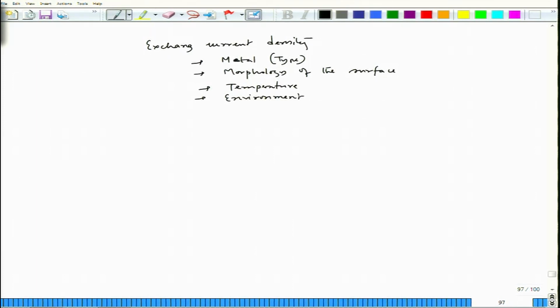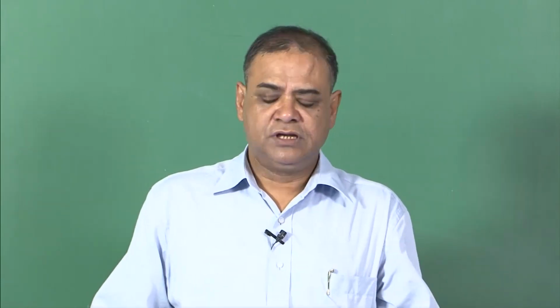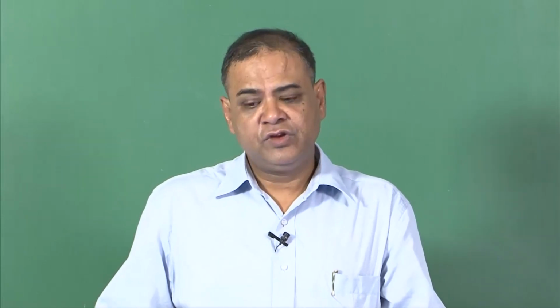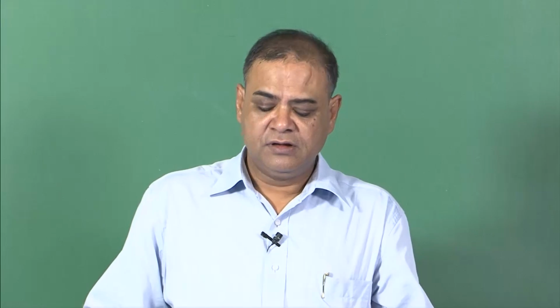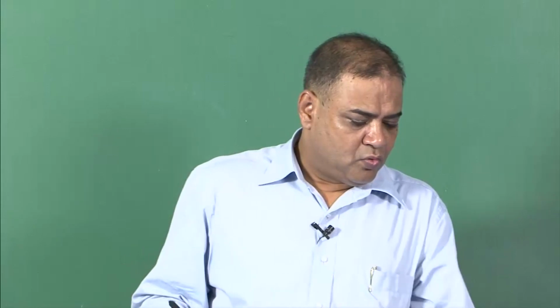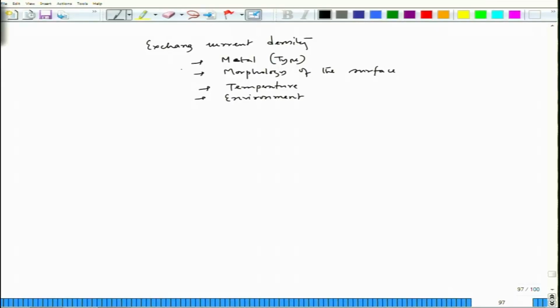Why environment? Because sometimes we have a situation like in one place we have higher salt content, or in another place we have less salt content. For example, in seashore area salt content is very high, and if we go to the Himalayan belt, the salt content would definitely be less. So, in those two cases, even if we use the same temperature and pressure and the same metal and solution, we would have a difference in exchange current density of a particular reaction. And then we have solution concentration. This would definitely change the exchange current density also. So, these are some of the factors on which